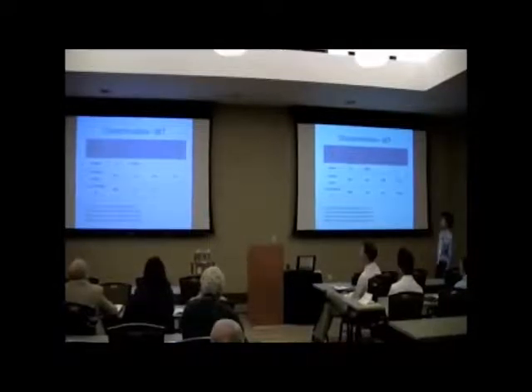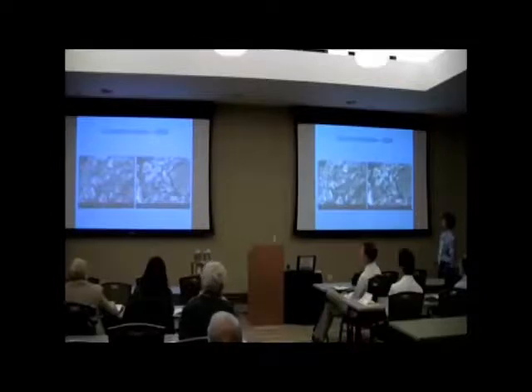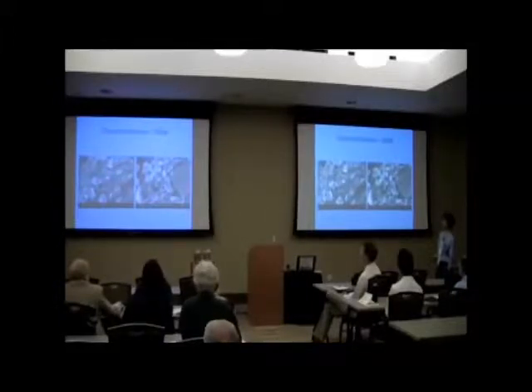After we modify it with the hydrogen peroxide, it goes up higher than the traditional active carbon. So we tested the scanning electron microscopy. This is the active carbon SEM image. We found that there's some kind of fibers in these materials. We think that this is probably a good material for the supercapacitor.